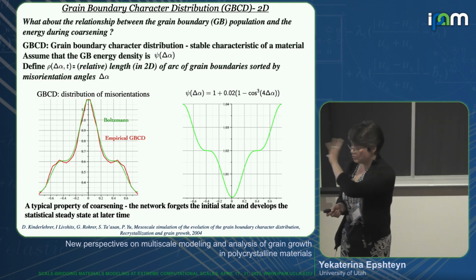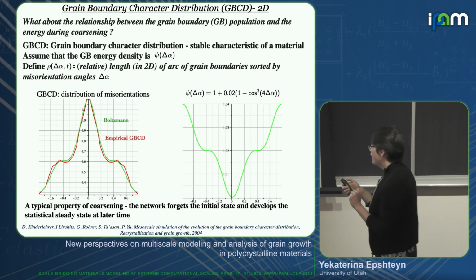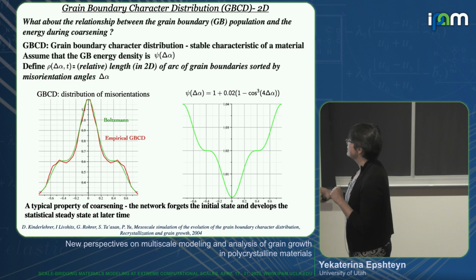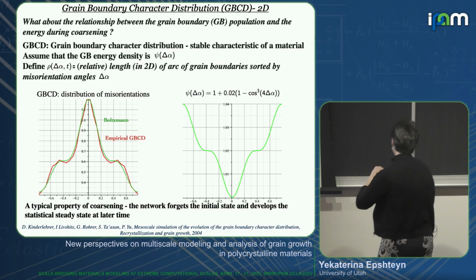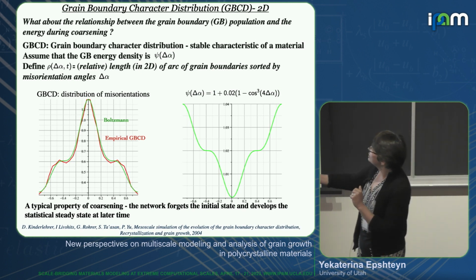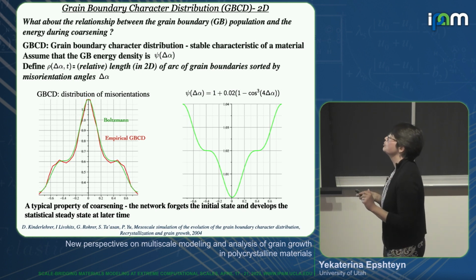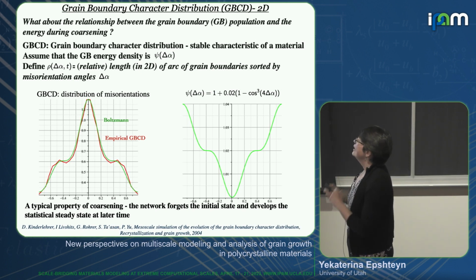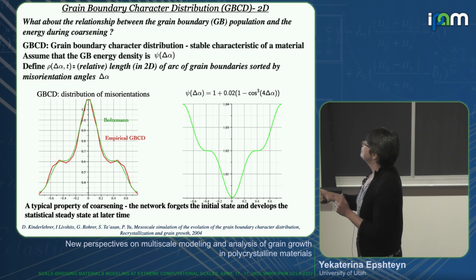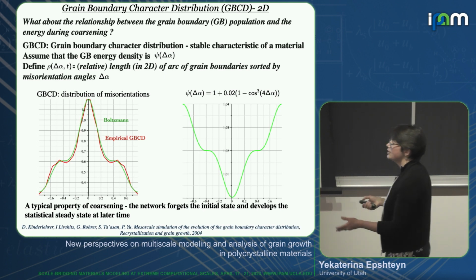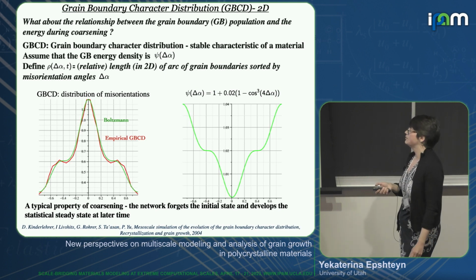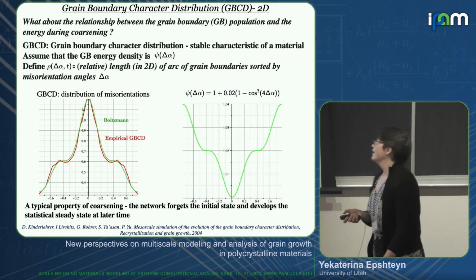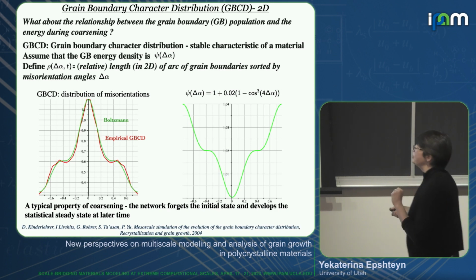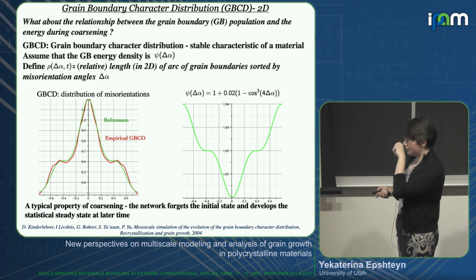And for my modeling goals, I will introduce it in a simplified setting for now. Namely, I will assume that the grain boundary energy density only depends on misorientation, and I consider at this point a 2D cellular network. So in that simplified setting, this GBCD is basically defined as the relative length of arc of grain boundaries that are sorted by misorientation angle alpha. So one can think about it as the probability of finding a grain boundary with a given misorientation angle alpha. And